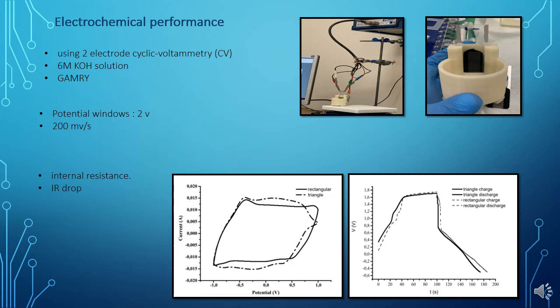We observe that the CV curves are rectangular in shape, which means they show electric double layer behavior, a characteristic of a supercapacitor. The area of the triangular electrode was bigger than that of the rectangular patterned electrodes. That means it stores more charge, and it has a higher specific capacitance than the other. Other curves are charge and discharge curves, where the shape of the charging and discharging curves was not triangular, which may be because of internal resistance. The charge-discharge time and IR drop of electrodes that have a triangular shape are lower than the other.